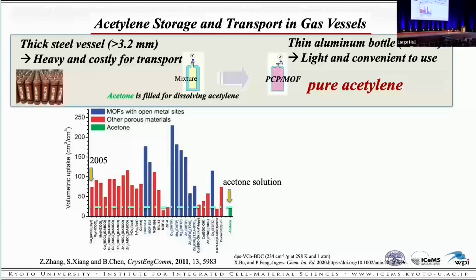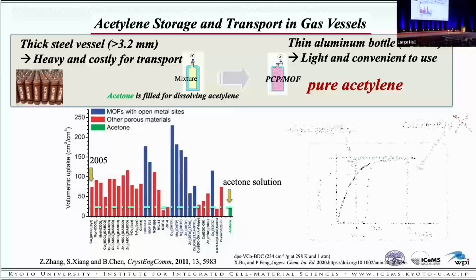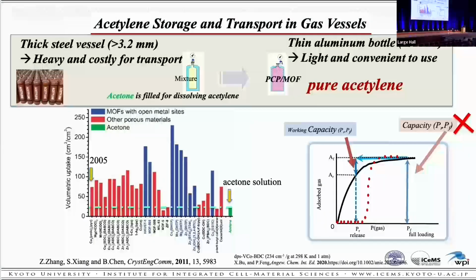Since we published acetylene storage in 2005, there have been many reports, as you can see here. The saturated adsorption capacity has been going up and up. However, when considering storage, it is not the amount adsorbed, but the amount that can be released. The working capacity is important. For this purpose, it is essential to develop a flexible MOF with an S-shaped adsorption isotherm, which maximizes the usable amount in a safe pressure range.